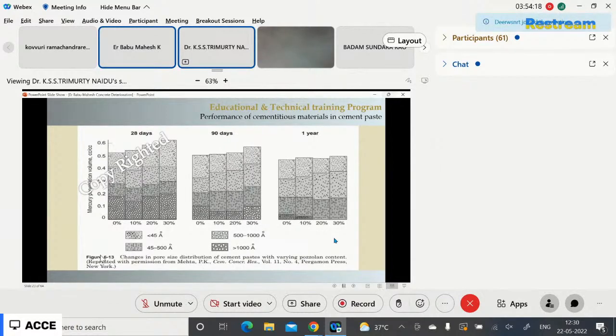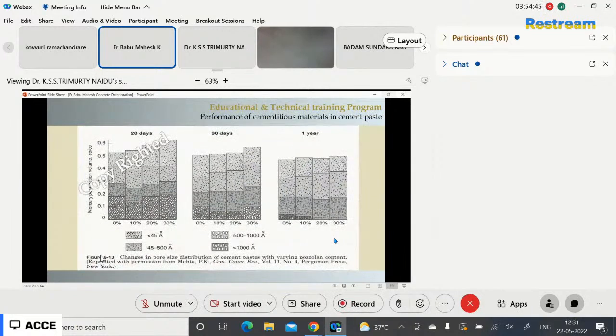This picture shows the pore distribution of the cement paste with varying pozzolanic cement content of about 10%, 20%, and 30%. We can observe a significant reduction in pores in cement paste at 90 days. And finally, no larger pores, that is greater than 0.1 micron, were seen after a year in cement paste where the replacement level is 20 and 30%. This is primarily due to the secondary C-S-H gel formation in the blended cements.